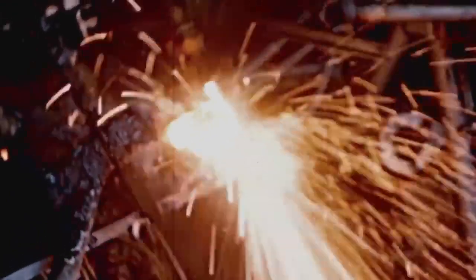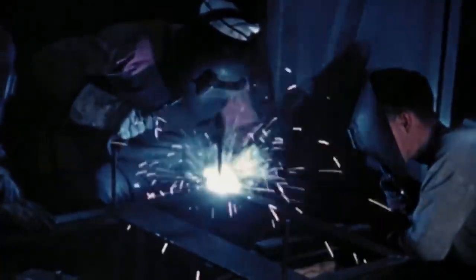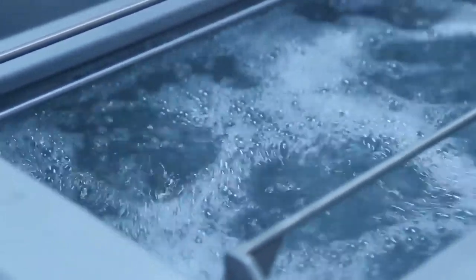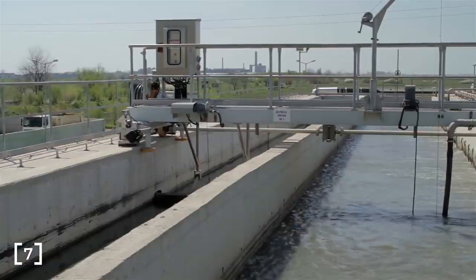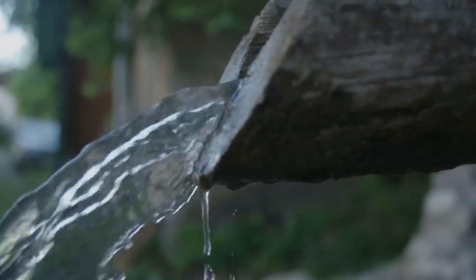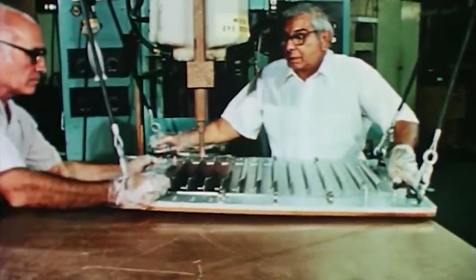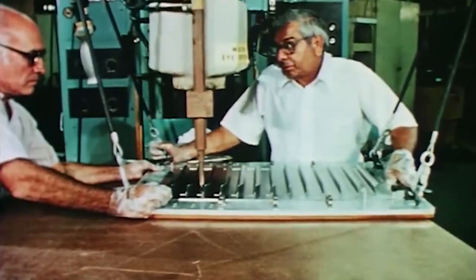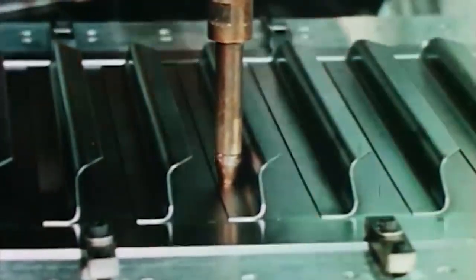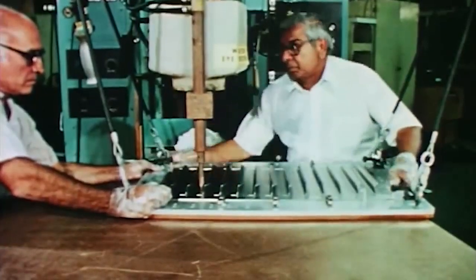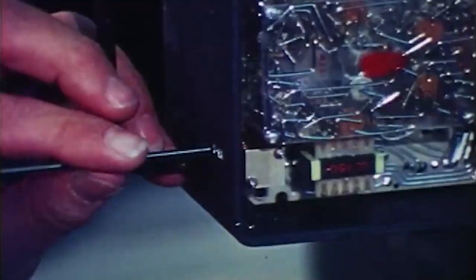They discovered that spot-welded parts made in summer were failing very early in their life, but those welded in winter were fine. They eventually tracked the problem to the fact that the Burbank water treatment facility was adding chlorine to the water they used to clean the parts to prevent algae blooms in the summer, but took it out in winter. Chlorine, as we saw earlier, reacts with titanium, so they began using distilled water from this point on. They discovered that their cadmium-plated tools were leaving trace amounts of cadmium on the bolts, which would cause galvanic corrosion and cause the bolts to fail. This discovery led to all the cadmium tools being removed from the workshop.